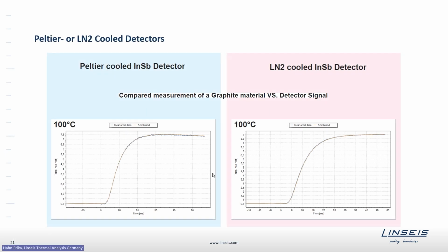I have also told you before that as an option for the detector, we have either a thermoelectrically cooled detector or a liquid nitrogen cooled detector. Here you can see the comparison of a measurement performed with both detectors at the exact same temperature, using the same material. What one can see is that the signal of the thermoelectrically cooled one is a little bit more noisy. However, it is still very stable and can be evaluated with a high precision.